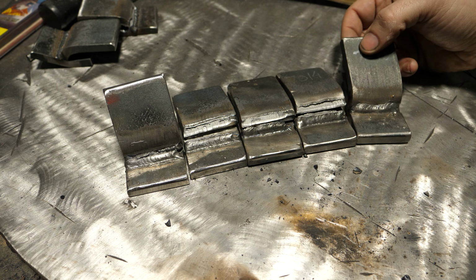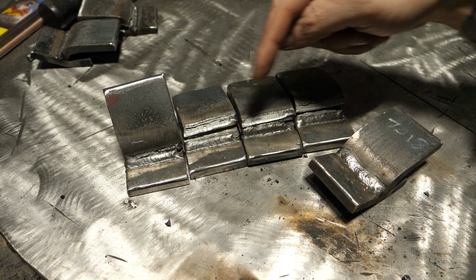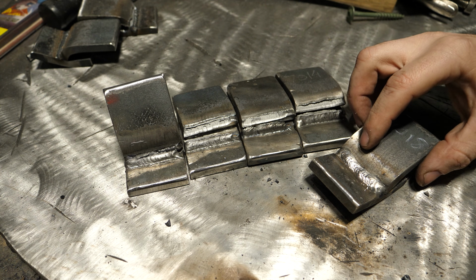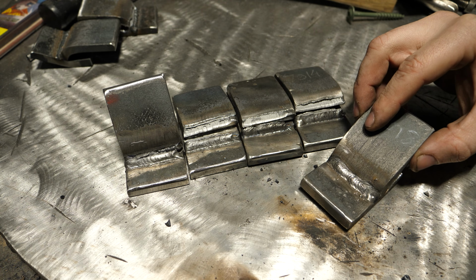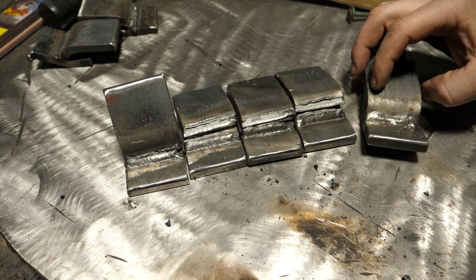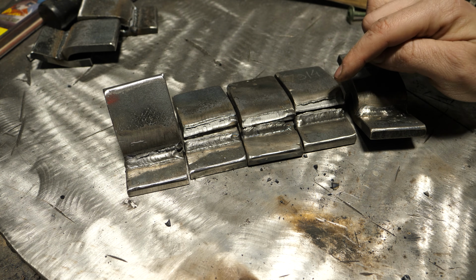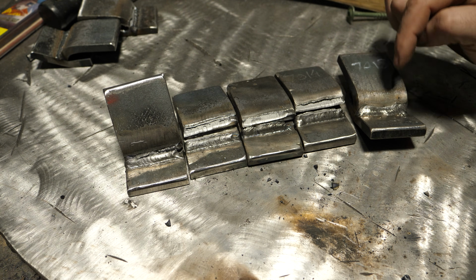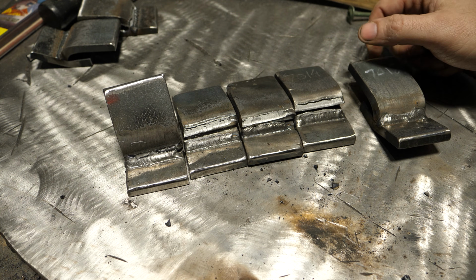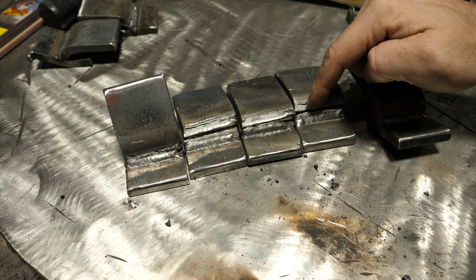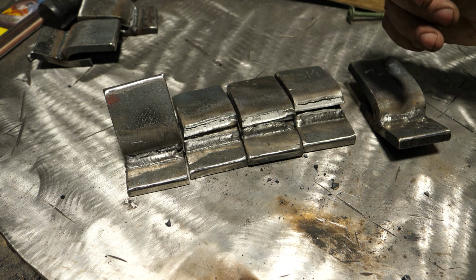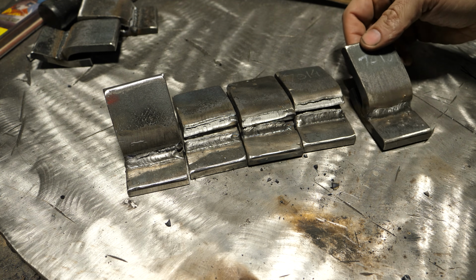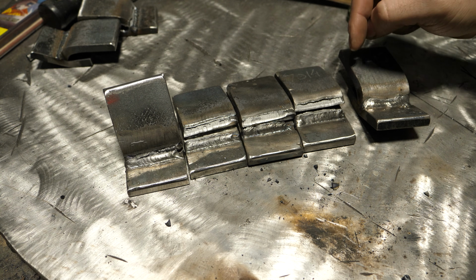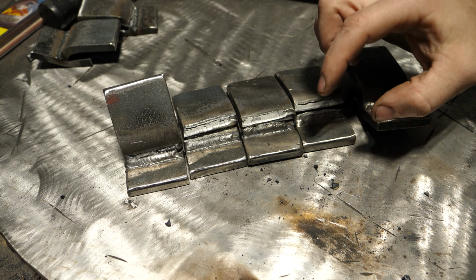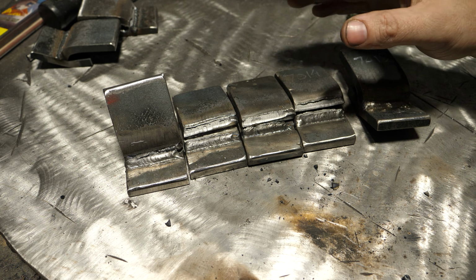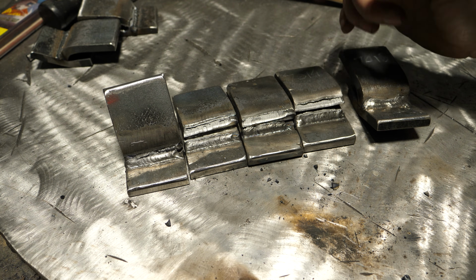What I mean by that is here's a 7018 weld that was stressed further than any of these. So a steeper angle, more pressure, and it is still together in one piece. So from my aspect, does it really matter if the plate or the weld is really to blame, if 7018 can surpass the strength, or ER70 MIG can surpass the strength of this rod? And my answer is, well, no. And coinciding with that, all of these are made with the same plate material, the same sizes of plates, cut from the same bar. So all of this is the same material, 100% all prepped the same. The only real difference is the rod I'm using.